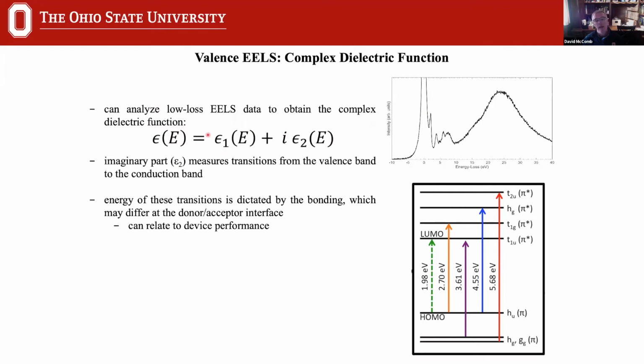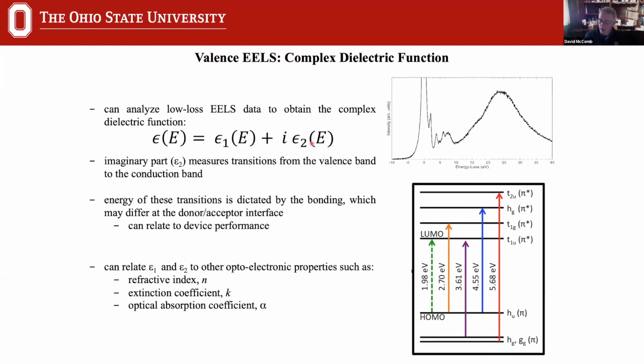And that complex dielectric function contains all of the information about the optical properties of the solid. And in particular, the imaginary part is really our absorption terms. It tells us about transitions, single electron transitions between the valence and the conduction band. We were able to isolate, using the dielectric function, the single electron transitions from those collective excitations. And the energy of those transitions are going to be related to the bonding, which may change as we look at different, for example, interfaces in organic systems.